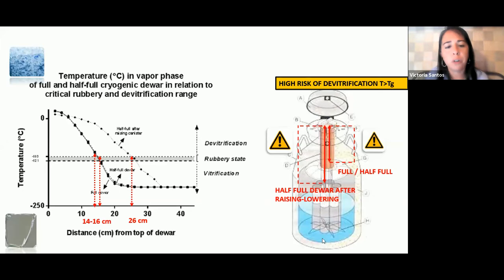This is another way of showing these results, that for a full or half full, we have the dangerous zone here at the neck between 14 and 16 centimeters. High risk for the devitrification since the temperature here of the nitrogen vapors is above TG. And for a half full after raising, we have a larger zone that goes to about 26 centimeters.